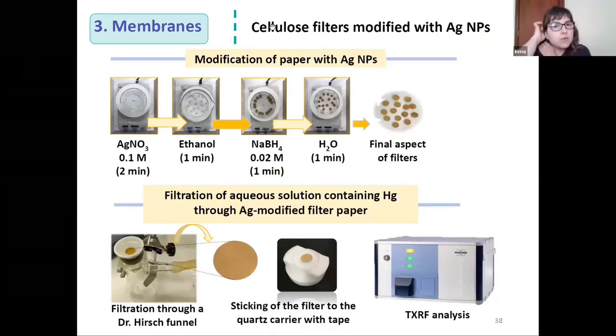One of the last works related with TXRF was performed with cellulose filters modified with silver nanoparticles. Here we can see the preparation of these filters. We have the silver nitrate, then we need to wash the filters with ethanol to remove the possible silver not retained into the filter. Then we perform the reduction with sodium borohydride, and finally we wash with water. And we have to air dry the filters to have this aspect.